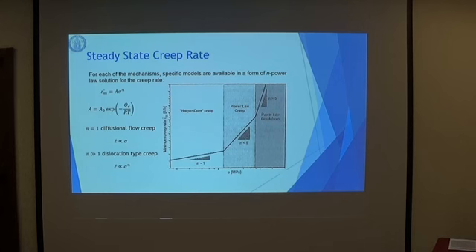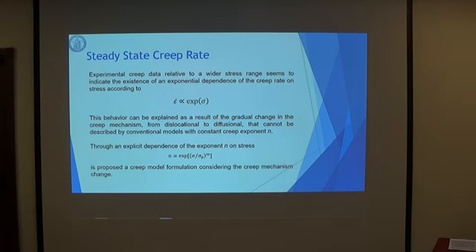That means that if we have a constant value of n and A, which can be, I don't know, 5, 10, in case of low stress value, the creep rate can be largely underestimated. So it seems that experimental creep data relative to a wider stress range indicate the existence of an exponential dependence of the creep rate on the stress. And this behavior can be explained as a result of the gradual change in the creep mechanism, going from dislocational to diffusional, so from high stress to low stress levels. And this cannot be described by conventional models with a constant value of the creep exponent n. So, through an explicit dependence of the exponent n on stress, here we are going to propose a model which takes into account the change of mechanisms from dislocational to diffusional.